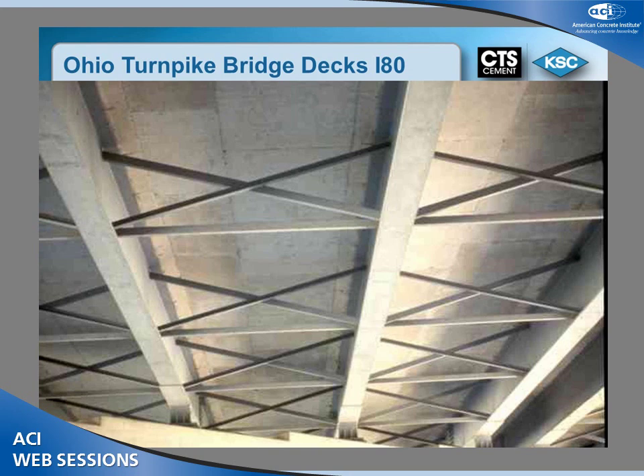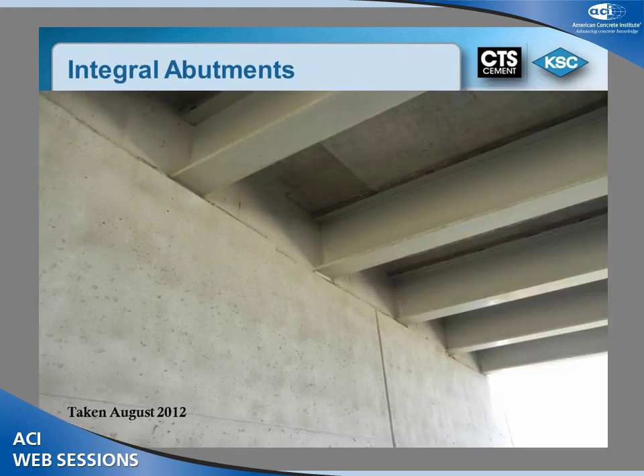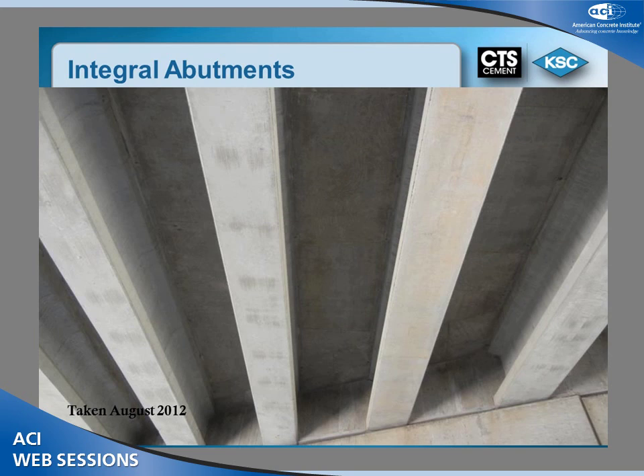Now, the question comes up, do we want to get a lower permeability? Well, yes, possibly, but at this time, in 1985, we were just now getting into the idea of looking for reduced porosity and reduced permeability. Something else that comes into play is the type of structures when it comes to the integral abutments. As you can see here, this was a steel girder cast into the concrete abutment. Here's the concrete version cast into the concrete abutment. And what we're finding is that on the concrete deck that's placed on top of here, there is so much stress from the shrinkage taking place on the deck that we're getting a lot of cracking. It's basically because the ends are restrained, and the cracks start showing up throughout the entire deck.